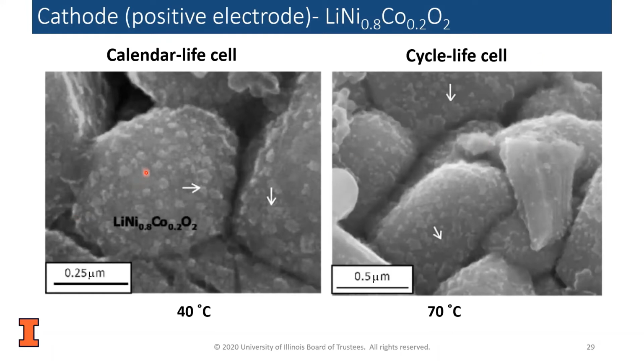And in each case, you'll see that we're developing a number of these little crystallites at the surface, and they're all localized. So it indicates that we're getting localized decomposition reactions at the surface. And eventually these crystallites will nucleate, form larger particles. And then, as you might imagine, once these particles get large enough, the battery's probably no longer useful.